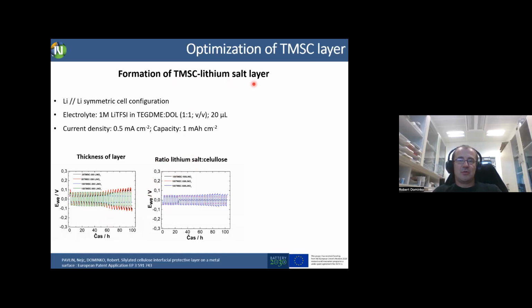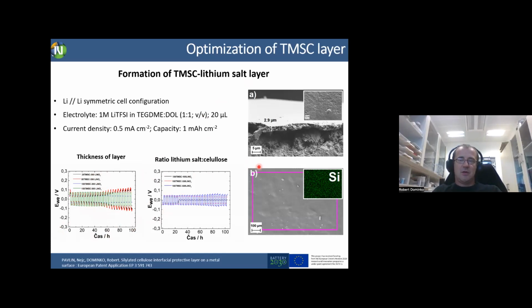But then there was a next step. We filled the porosity with lithium salt. The idea was to fill it with lithium nitrate at the beginning, because we knew that lithium nitrate has this healing formation of the passive film, it forms a very good passive film. And if there is some new passive film formation, there will be enough salt in the pores of the cellulose which can heal the further degradation of the metallic lithium. So after some optimization, we came with the optimal configuration. And you can see here a top-down view and then a cross-section.